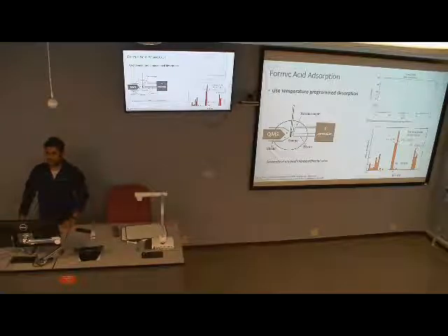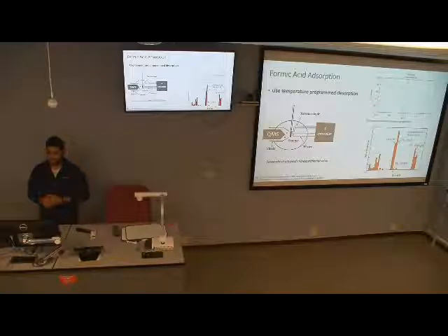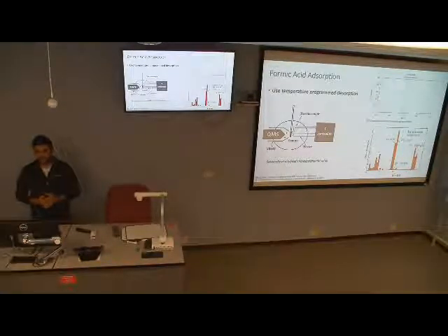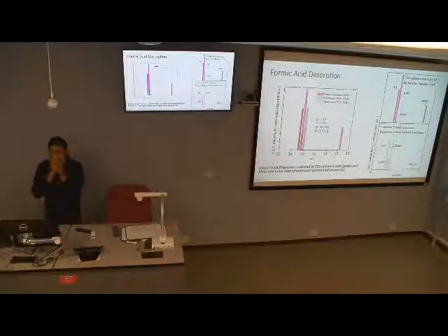Any mass spec dissociates molecules; that's how a mass spec works, right? So the deviation is the effect of the perovskite layer. If the pattern looks the same as the gas phase, you have intact molecules entering the mass spec, so you have molecular adsorption. But if the patterns are different, then you already have fragments going into the mass spec, so some dissociation is going on.